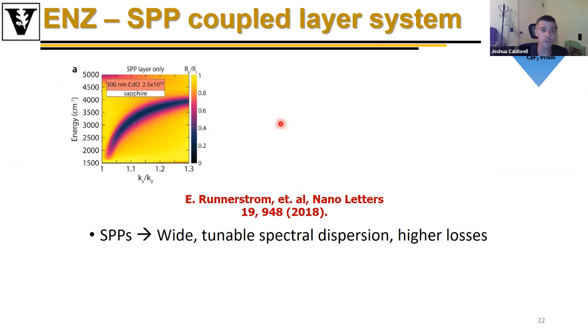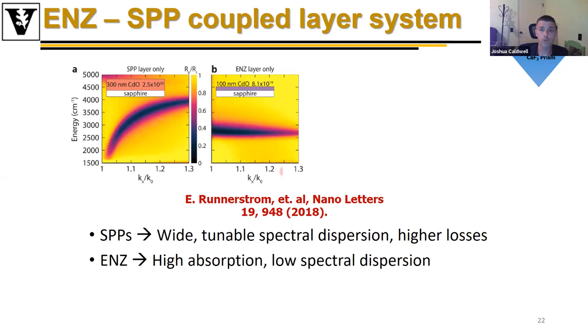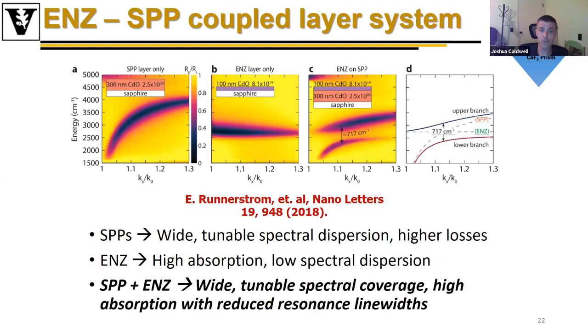In this case, we used a purely cadmium oxide structure on an R-plane sapphire substrate, taking a thicker layer that supports a surface plasmon polariton. I can then grow a layer on top of that, which is an ENZ polariton layer. By doing that, the ENZ polariton and the surface plasmon polariton can strongly couple together, again leading to this anti-crossing. One interesting aspect is that this anti-crossing is on the order of 30% of the operating frequency, which means this is approaching ultra-strong coupling.